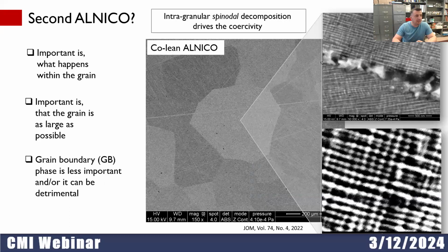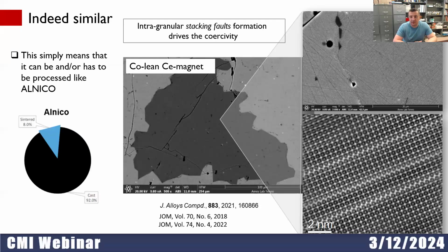So then, this gave me an analogy to what I did before, because I was working on Alnico. Alnico is a system where you also develop some kind of intragranular microstructure. And in our system, in this CGM system, we also develop intragranular microstructure. Coercivity is appearing not because of the grain development and sintering. Coercivity is appearing because of something that happens within the grain. For example, in alnico, we have spinodal decomposition, which is happening within each grain of the material. And here we have another kind of decomposition, but it is also happening within each large grain of the material.